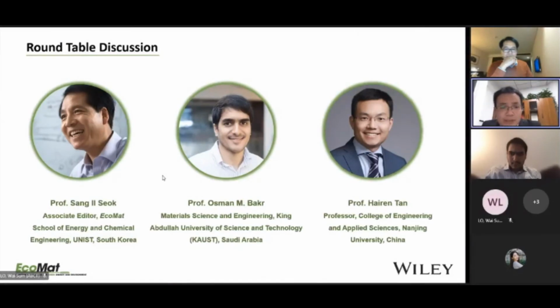Some studies also found that if the tin ratio is low in the material system, usually the defect formation energy is lowered a lot. So it means the material tends to form a high trap density, and the energy levels are shifted to the middle of the band gap. That means the material forms quite a large number of deep trap sites. That is quite bad for the device performance.